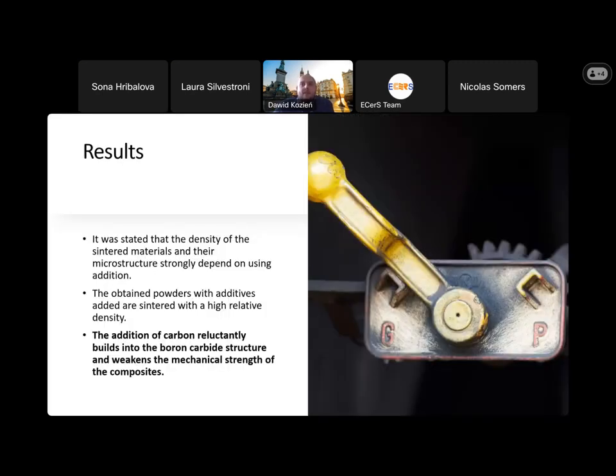So to sum up, what I found during my PhD was that the density of the sintered material and its microstructure strongly depend on the additions used. That is obvious. The obtained powders with additives are sintered to a high relative density, but the addition of carbon reluctantly builds into the boron carbide structure and weakens the mechanical strength of the composite.